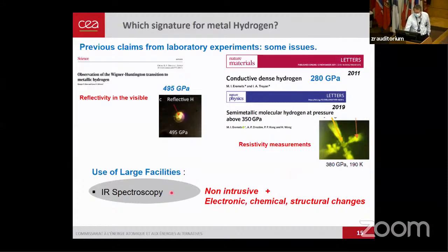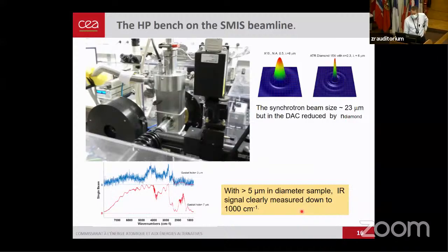So we decided to do non-intrusive, optical measurements, doing infrared spectroscopy. You can address, as we will show you, the electronic properties of the sample, and the chemical change, or if there is not much chemical change, the chemical bond of the molecule. And you can also follow the structural change indirectly by following the signature of the excitation modes. So a high pressure bench was built on the SMIS beamline, and the sample was in a cryostat at low temperature, and we also have Raman measurements that we can shift.